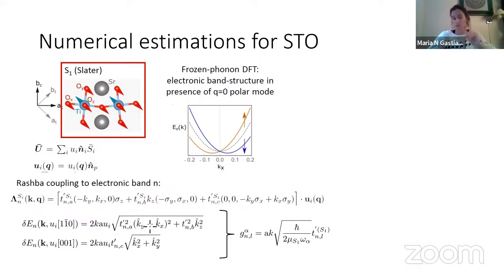So essentially, looking at different momenta directions, you can extract these T primes, and then you just plug them in here. You have the reduced mass and the frequency of the mode from experiment, which I'm taking from the coupling problem I solved for superconductivity in the paraelectric phase. So I'll take those values from there. I know what the T prime is, and then I know what the electronic filling or Fermi energies are. So then I also know what the relevant momenta is. So that's what we did.